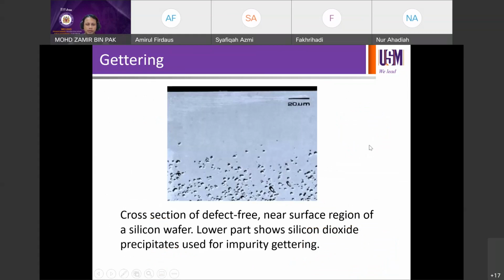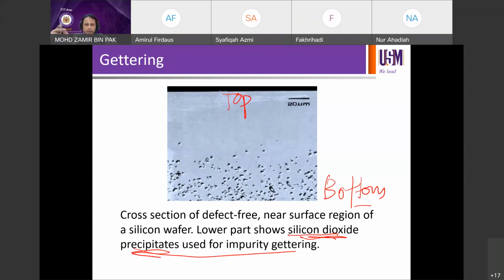So this is a cross section of a defect-free near surface region of a silicon wafer. That is the top surface, and this is the bottom area. The top is defect-free. The lower part shows silicon dioxide precipitates used for impurity gettering. So we use silicon dioxide in order to getter. Silicon dioxide is just a platform or medium for you to gather the impurities, and then eventually the silicon dioxide will be removed altogether from the silicon, even though it's already in the passive region. We still remove it anyway.